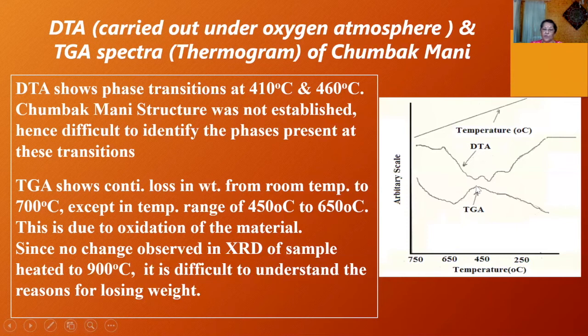And this is due to oxidation of the material, as we said earlier. Since no change was observed in the XRD of the sample, even when it was heated at 900 degrees centigrade, it becomes more difficult to explain the loss in weight. Had there been any change here? So whatever we got and whatever was there, even if you anneal it, it doesn't alter the characteristics.